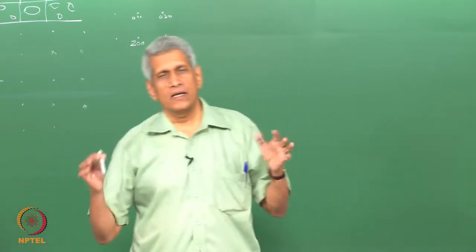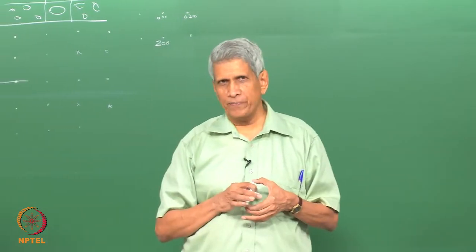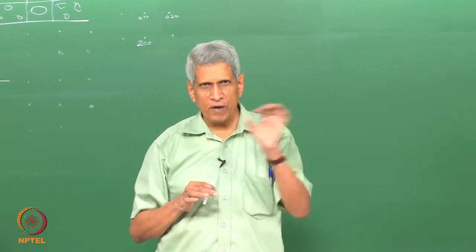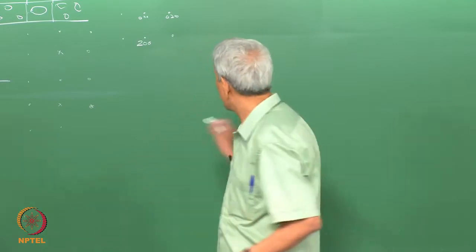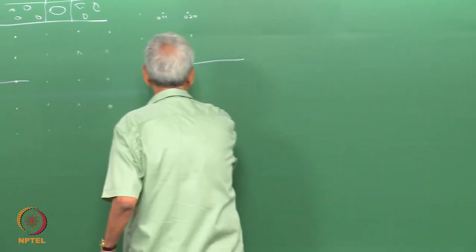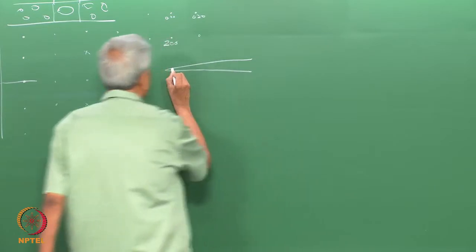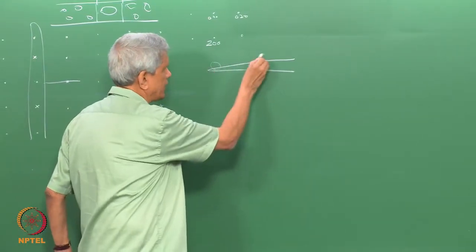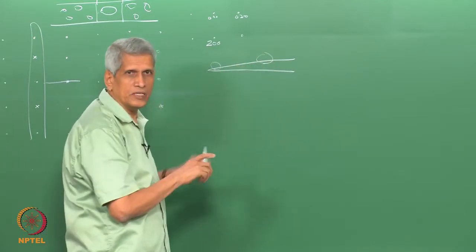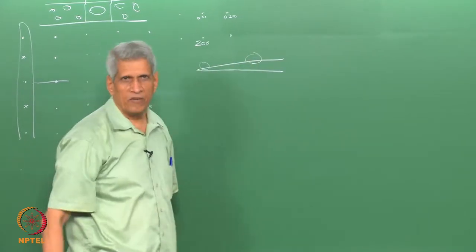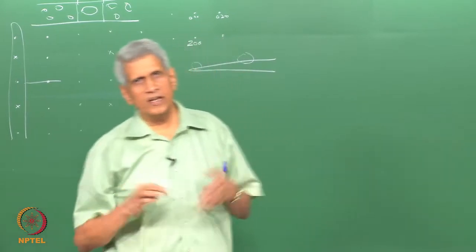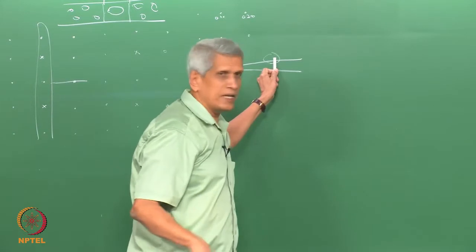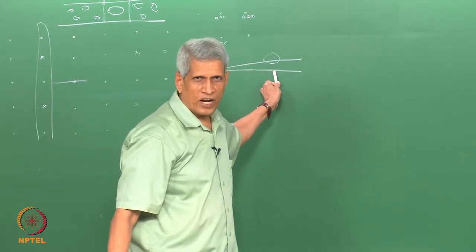That is, if we take a sample which is an extremely wedge-shaped sample, like we have a sample like this and the thickness is very small in this region. If I take a diffraction from this region, I may not see the double diffraction. If I take it from this region, the probability of double diffraction increases.